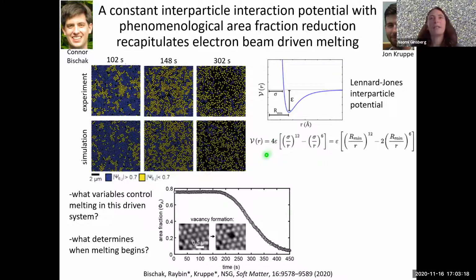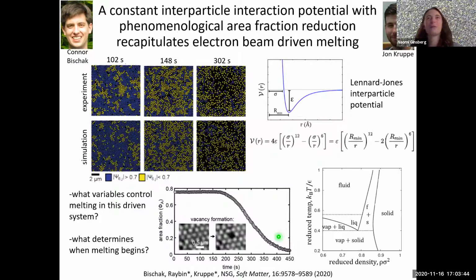So we added to that a phenomenological particle deletion protocol that basically follows the experimentally observed reduction in the area fraction as a function of time. And interestingly, we don't have to change the Lennard-Jones parameters as a function of time, even though the electron beam continues to illuminate and drive the system. Okay, so the system seems kind of immune to those. And so interestingly, the decreasing area fraction basically drives the melting, so basically translating horizontally somewhere on this phase diagram, but not changing anything vertically.